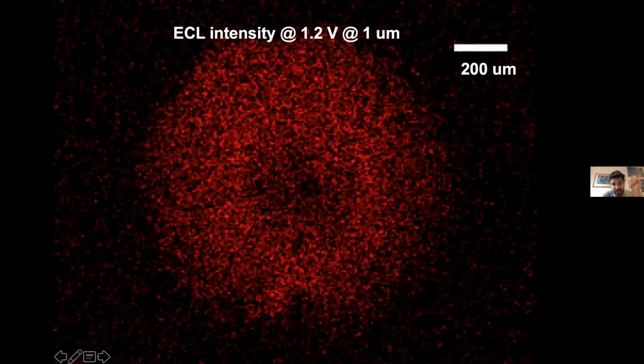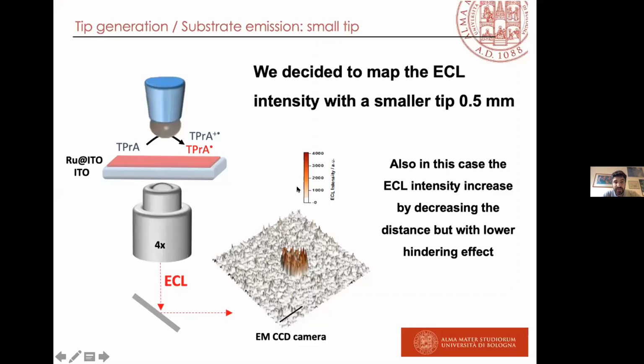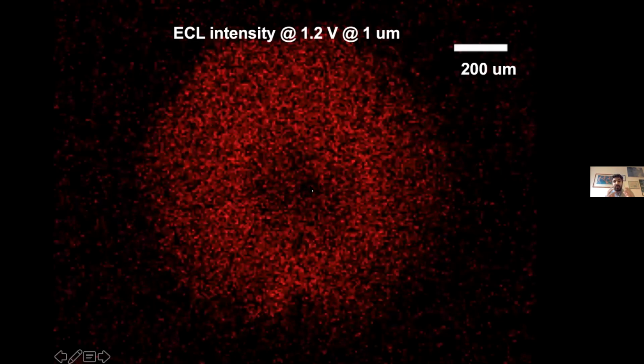We have a donut shape, so black dots in the center of the ITO substrate. So emission, but black dots in the center. And this is very well known in the field of scanning electrochemical microscopy. It is due to the hindering of the TPrA. If you have your tip very close to the substrate, you have the hindering of the TPrA due to the shape of the tip, and so in the middle you cannot have a strong, homogeneous emission like in the donut shape.